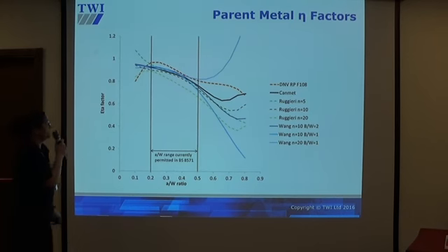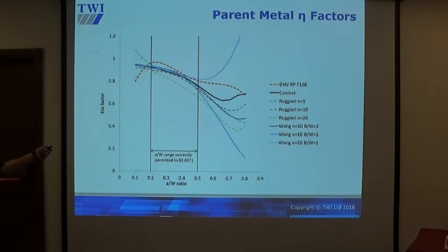And I was quite pleased because the Canmet seems to be quite a neat fit to the general mean here, but it's playing in my mind that where you have particularly high strain hardening, it may perhaps be a little bit over conservative. The DNV, despite having this 0.85 safety factor, still seems a little bit high relative to the other alternatives.